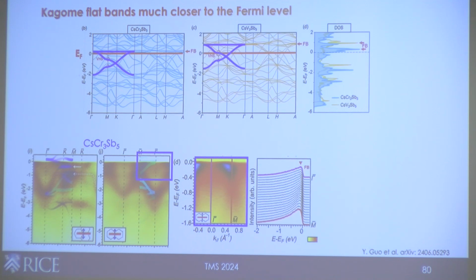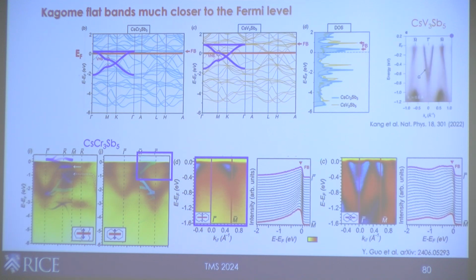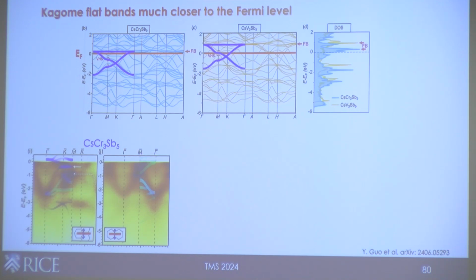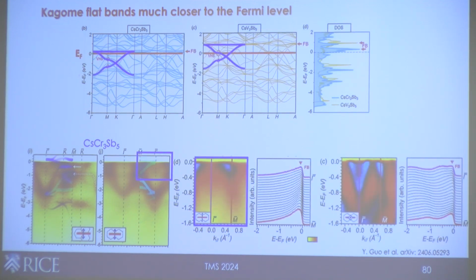Another way to see this is to compare with the vanadium version. In the vanadium version, for those of you familiar with the band structure, around the gamma point there's an electron band. You can see it's very clear here, nothing there. But in the chromium version, if you take a line cut here, you actually see a peak appearing within this electron pocket. Why is that important? If you look at the DFT calculation, this is the vanadium pocket, and the next band up is the topological Kagome flat band, which hybridizes with the vanadium electron pocket. So this suggests that in this system, the flat band is much closer to the Fermi level even compared to the DFT calculation.